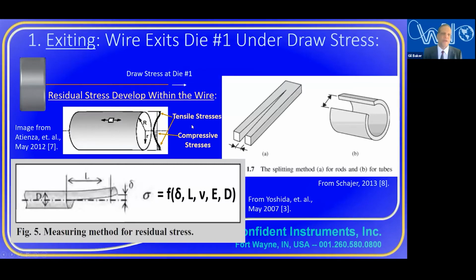So there are residual stresses in the wire coming out of the die. Well, the wire comes out without any residual stresses, but there are temperature gradients in the wire. Typically at the speeds we run in production, the surface temperature of the wire is going to be much hotter than the center. So as the wire comes out of the die, the surface is going to contract as the temperature equilibrates and there's a little cooling at the surface. So it's got the tension pulling it. That tension pulling it causes a compression at the center. So now this is what we have in typical manufactured wire. We have residual stresses, and we're again calling these axisymmetric residual stresses. It's symmetric about this line.